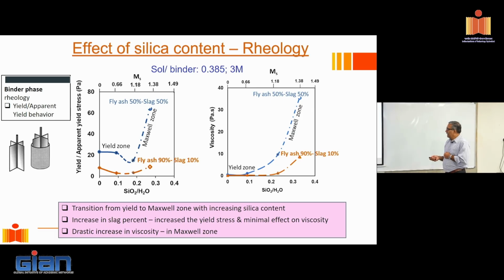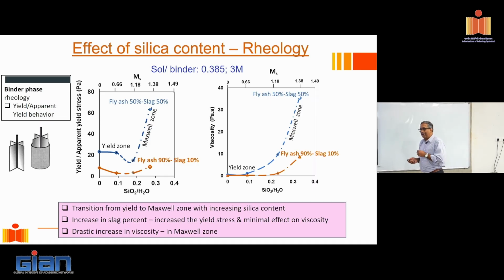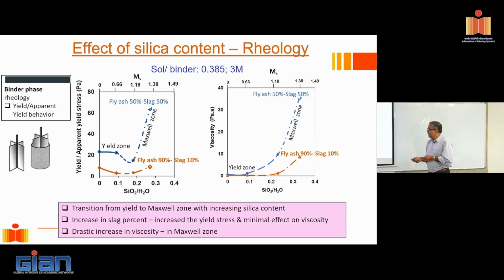And notice what happens to the viscosity of the paste when I increase the silica content. Okay, the viscosity just shoots up. Right? As it is, I'm dealing with a viscous solution. If I add more silica to it, what will happen? It will only make the paste more and more viscous. If I add more silica to the solution, I'll transform from something that may have a yield type behavior to a Maxwell type behavior.